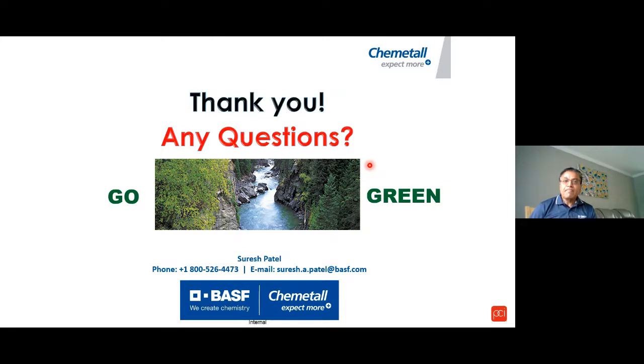All right, and I don't know if you would be able to answer this because it may vary, but how many minutes of wash per bath for the zirconium application? Let's call an average 45 seconds dwell time. I think that is what the question is, correct, Kevin? I just read what was written. I can't know for sure, but I think that's what it was. Yeah, if you're talking about the dwell time, or how much time you would need to apply to the parts with the zirconium pretreatment, average 45 seconds. Can some people run at 30, 35? They are. Some people are running at 1 minute. If you are running longer, you want to use a lower concentration. If you have 30 seconds, you want to run on a high end of the concentration of the zirconium.